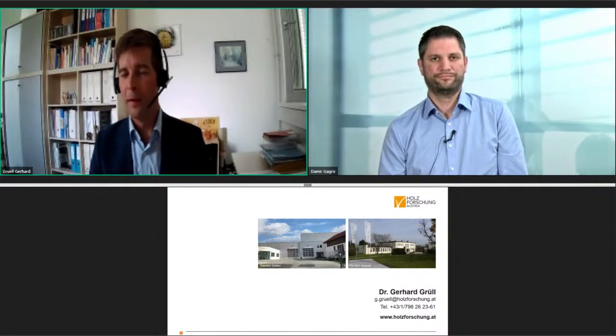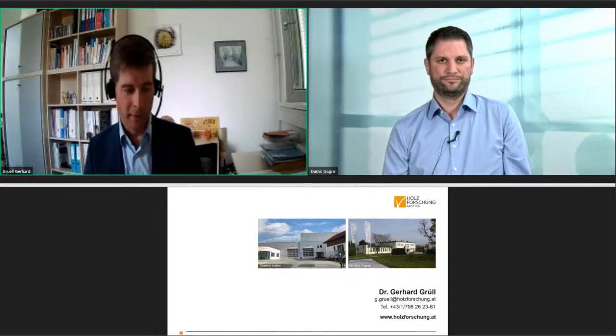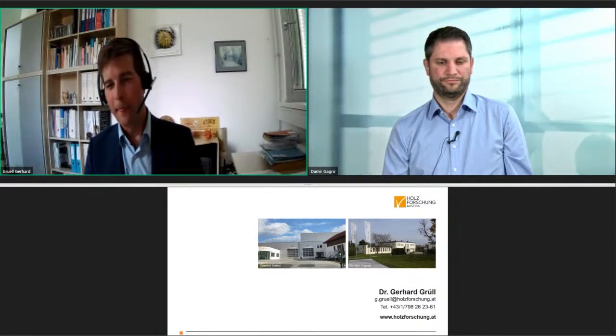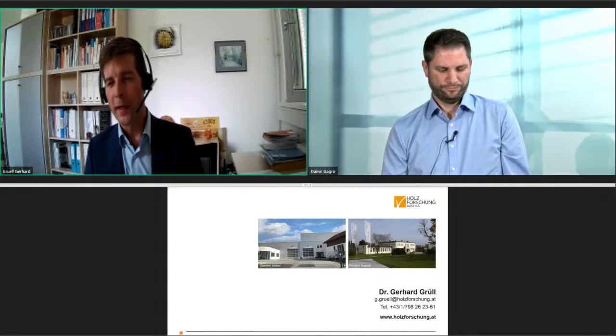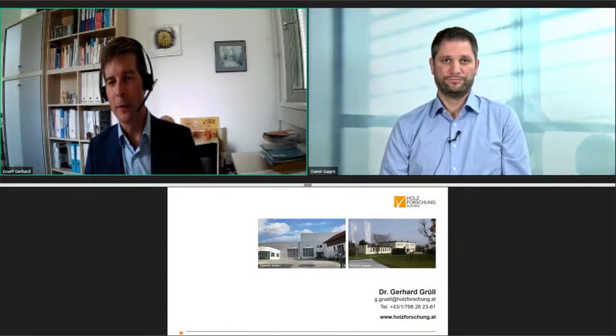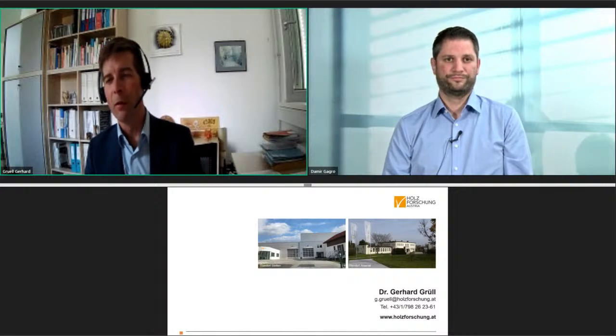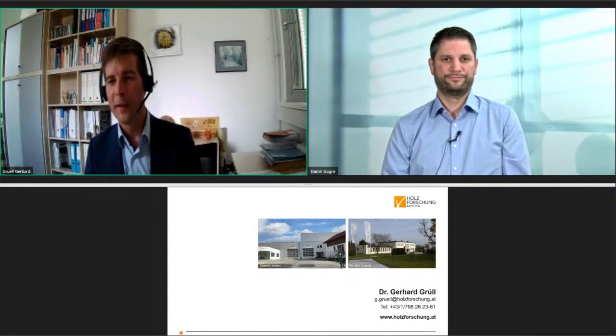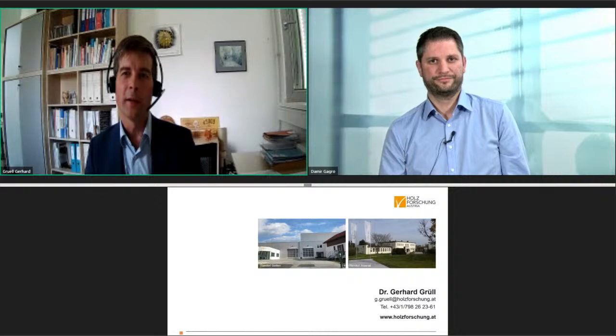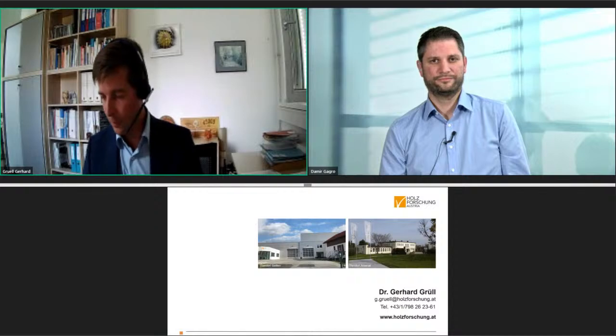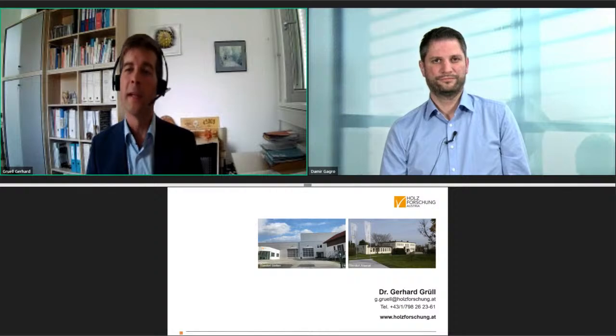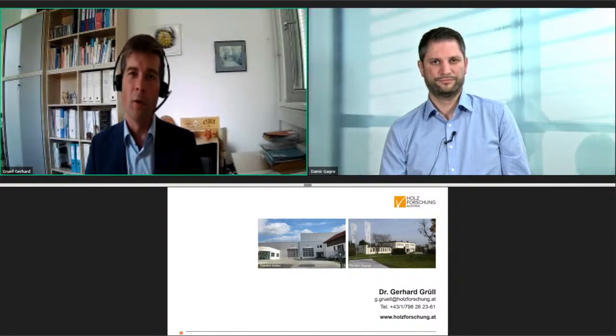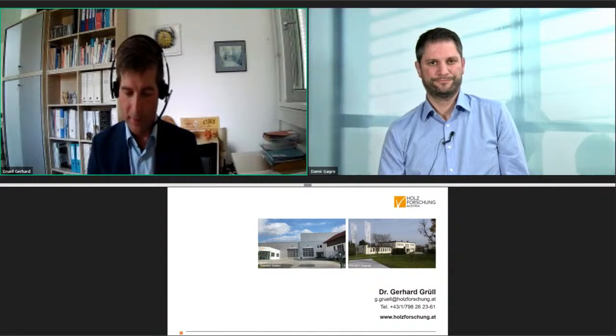I've shown this example of this facade in the last slide, which was originally a transparent coating, and over time, during some maintenance coats, it turned to be pigmented, and in the end, it could be an opaque painted surface. Why not? So with maintenance, you could also change pigmentation, add pigmentation, and thereby retain a nice optical view of the building. We don't need to have the demand that this transparently coated surface must remain a transparently coated surface over all the lifetime of the building. This is very, very demanding, of course.